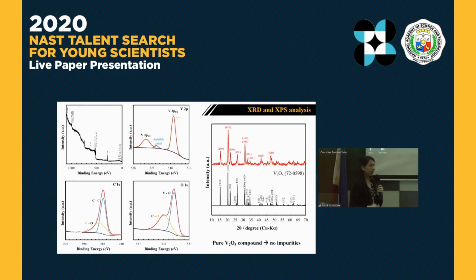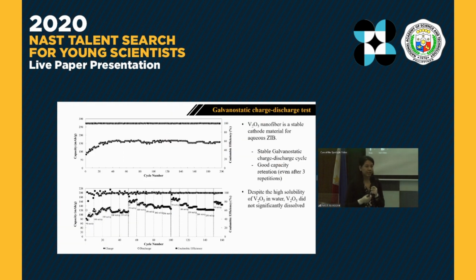So to examine the purity of our sample, we examine our V2O5 under XRD and XPS. So based on our result, the produced sample is a pure V2O5 compound without any impurities. So we examined this sample under galvanostatic charge and discharge cycle and found that V2O5 nanofiber is a stable cathode material for aqueous zinc-ion battery.